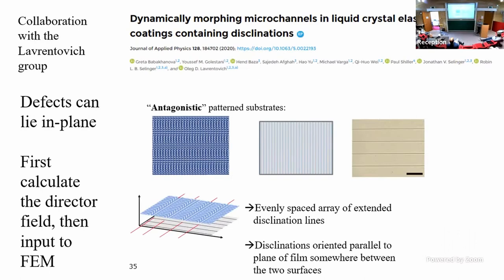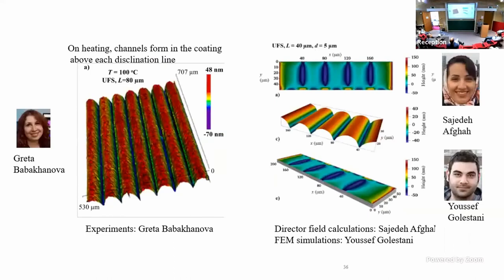And then we remove one side or the other of the glass and we have a coating. And when you heat it, you get an array of microchannels. Okay, so this is an experimental study again by Greta Babakhanova. Here's a simulation done by Yusuf Golestani with the finite element simulation that produces those beautiful channels.